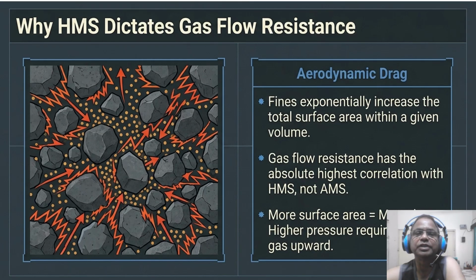So the effect is, for your daily shift, when HMS drops, the pressure required to maintain your wind volume goes up. If you hit the blower's limit, you have to cut wind, which means you lose productivity. Protecting HMS is quite literally protecting your plant's bottom line and total metal output. So let's put some real numbers to this so you can see how the math actually works in the lab.